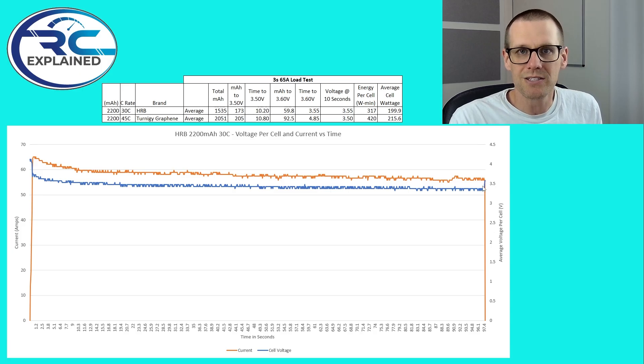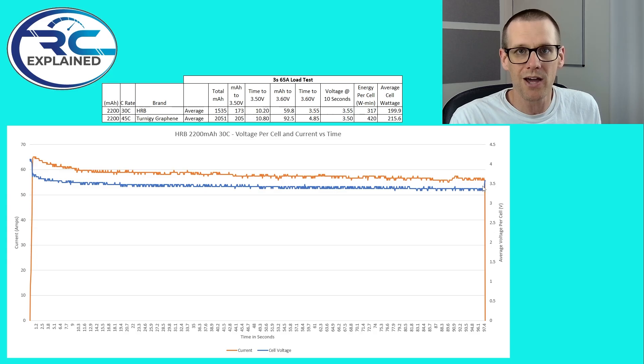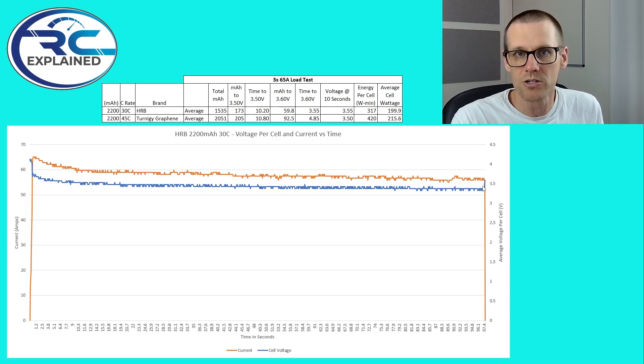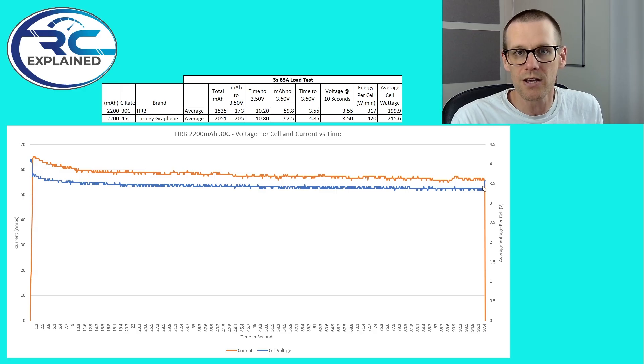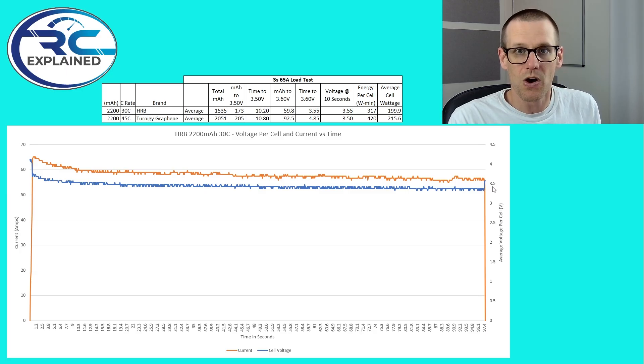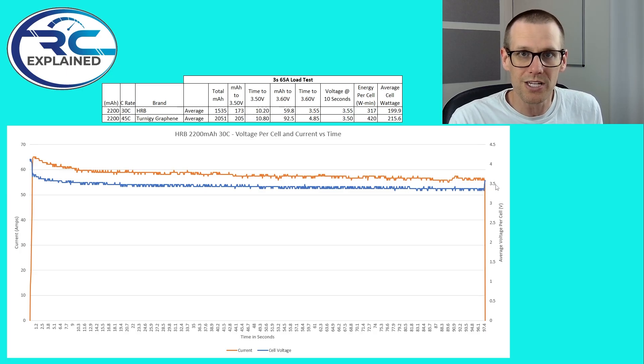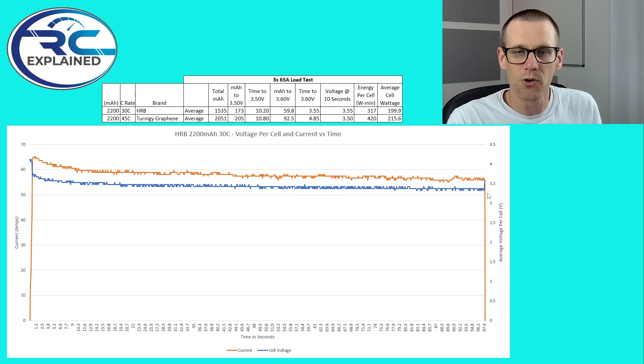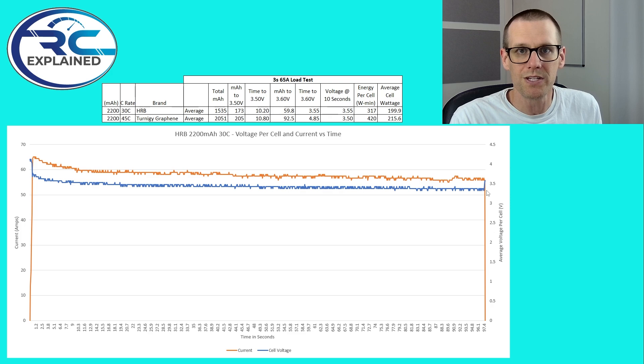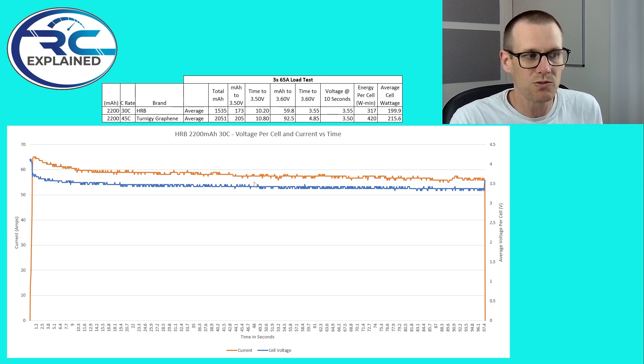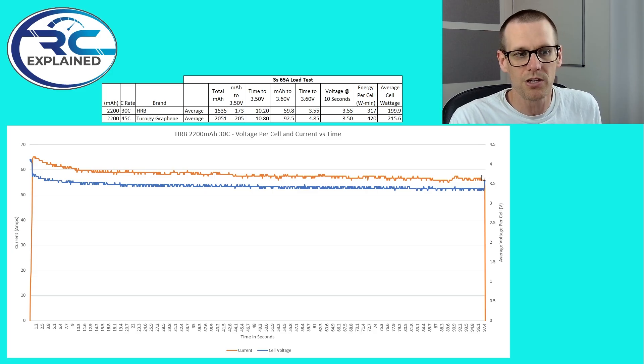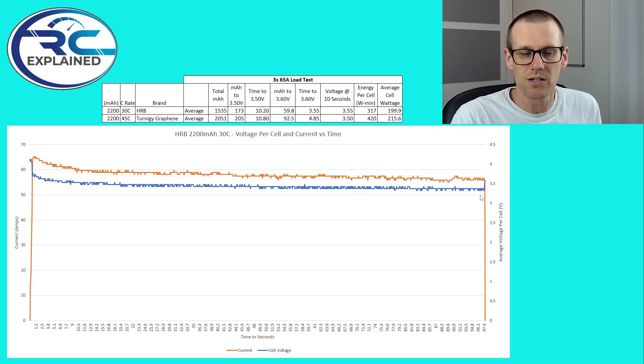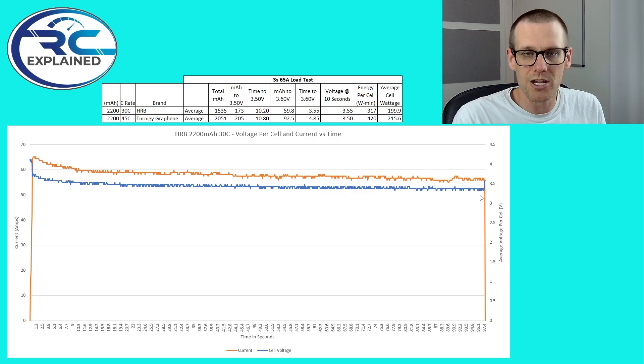This ended up having to have the run cut. So I did have to cut both of these battery packs. I did cut the one with lower internal resistance a little bit later, but it did have to be cut as well. And it could not withstand the full duration under load at this load. So our calculator there for a real C rating said it can only deliver 51C. We've confirmed at 57 it cannot do that. It is definitely lower than 57 amps that this thing can deliver on average. And that's what our average looks like for the most part. So that's why you see the voltage rebound here and current goes to zero because I cut it off and everything sits at zero and the voltage rebounds. And that's our result for the HRB.